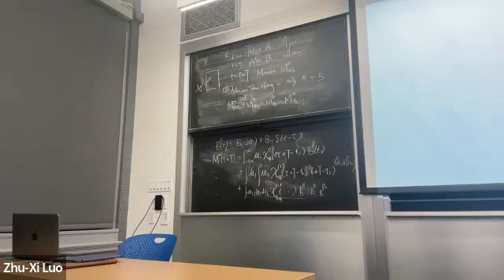And basically, for each momentum k, you have a two-level system, the level corresponding to whether the spinon is present or absent. The setup would be J exchange, ZZ, and you have a transverse field X. You will be interested in the B field in the X direction, because this will excite your domain walls. You're in the ferromagnetic ordered phase. And for this one, the spectrum dispersion is lambda k, the square root of J squared plus h squared plus 2Jh cosine k. Okay. And then you can calculate everything.